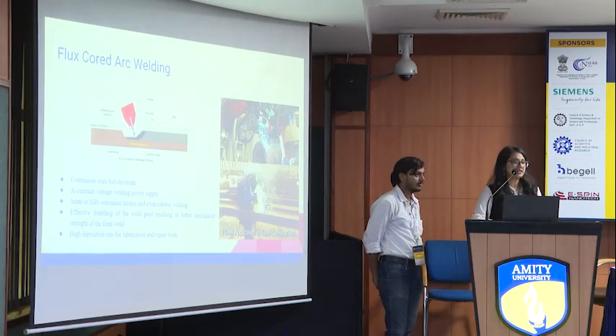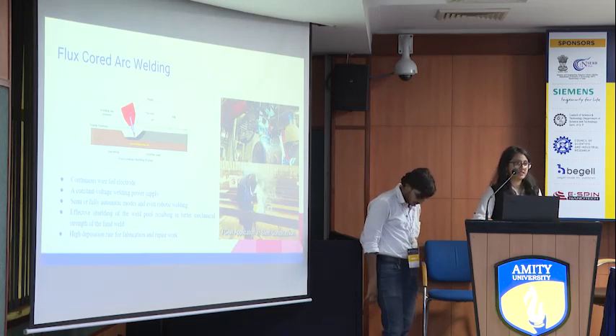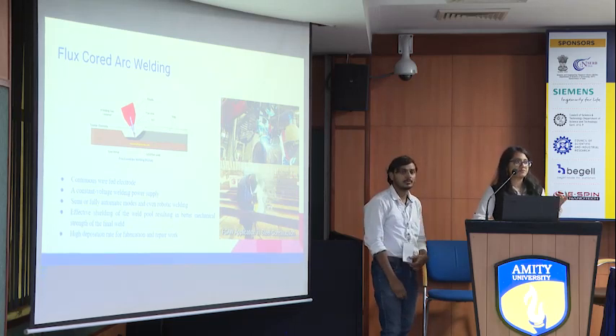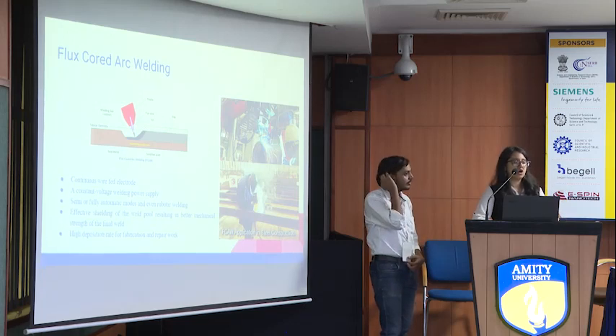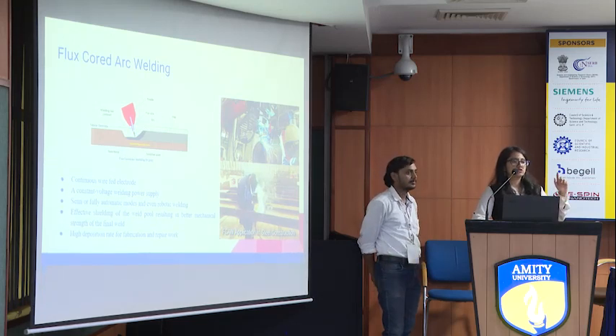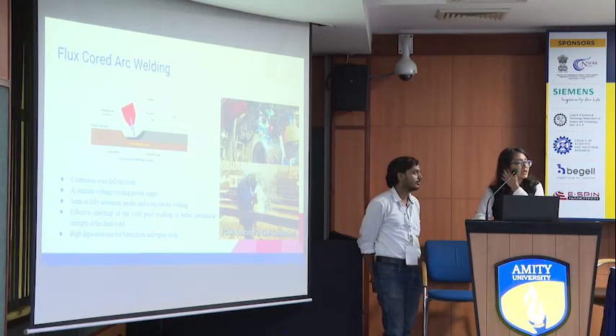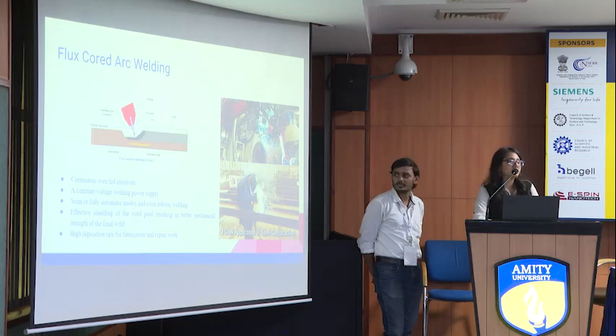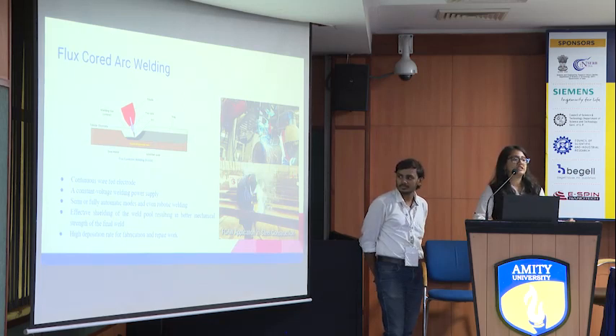Flux core arc welding. During the process of flux core arc welding, a continuous wire-fed electrode is fed onto the base material through a spool. A constant voltage welding power supply is maintained. This method can be automatic, semi-automatic, or it can even use a robotic arm. In this process, we usually use a shielding gas to prevent the weld from oxidation.